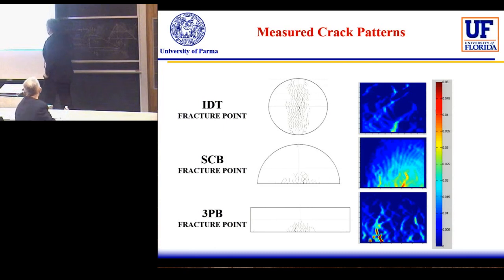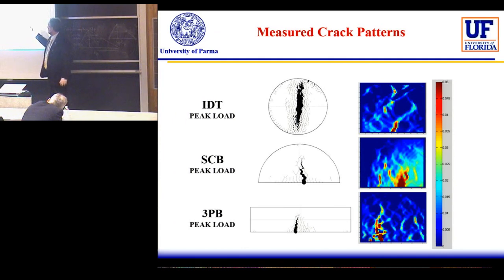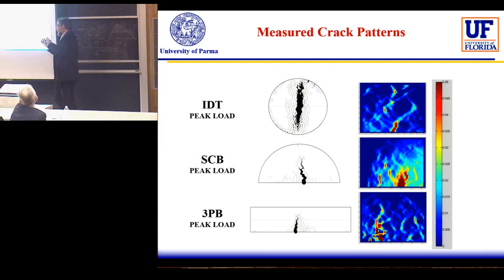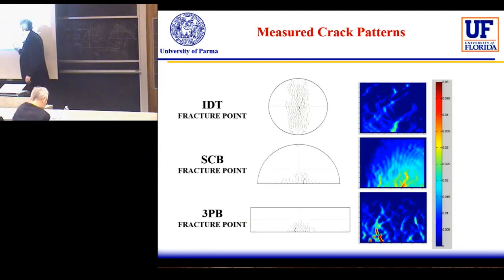So, looking at the crack, this is just a collateral result, the crack path measured, and this is just a representation. Here is the point where we calculate the fracture energy. You can see that even if the crack is not visible on the surface, the strain field is able to show that something is happening inside the material. And we know that because we are looking at the same point when the crack is visible. So at the peak, in this case the peak load, at the peak of the stress and strain curve. So the process was exactly the opposite. We identified the point when the crack was visible, and in the analysis we went back until the first change in the strain field was visible in the material. And this was the point that we selected as the first crack.